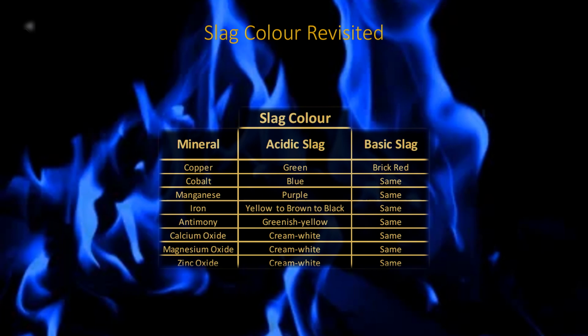Fire assaying is basically used for the pre-collection and the collection of the gold, silver, and platinum group metals. The calculations for the slag creation for the correct flux recipe are adjusted to mitigate any errors or problems which are associated with certain metals or minerals, especially copper, nickel, zinc, selenium, and tellurium. The resulting slag will be either acidic or basic.